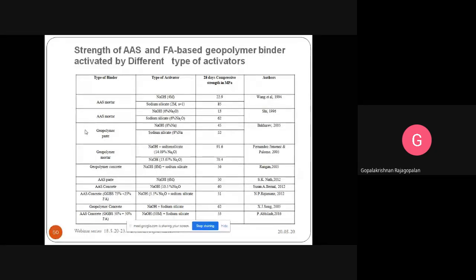Mainly, the geopolymer concrete depends upon the different types of activator we are using, whether sodium hydroxide or sodium silicate, or potassium hydroxide or potassium silicate. From my experience and my research work, I have tabulated some of the researchers who have worked with different types of activators and found the compressive strength values. This is the summary of the different types of activator, what they used and what compressive strength they got. This table gives the idea of which type of activator we have to use for the construction purpose or preparing the geopolymer concrete. That is the basic. I have just shown the table to you. These are the data we have to keep in mind while preparing the mix design of the geopolymer concrete.